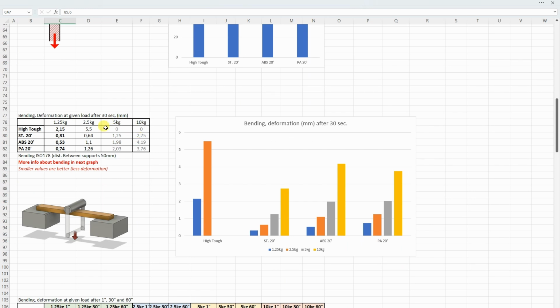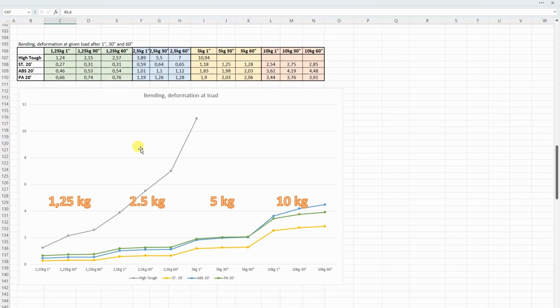The bending test, now this is the deformation after 30 seconds only under a given load, but more useful is this table, well actually this graph. And here we can see that even at 2.5 kilograms, this is almost linear, so it didn't stop creeping, with deformation, and at 5 kilograms it completely deforms. Until other series resin could survive even 10 kilograms. Of course, there was creeping, but they are holding the position.